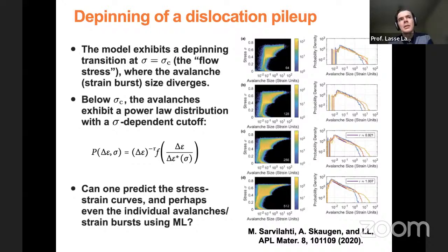And so now we would like to understand what we can say about this system. Of course, this system is a bit different from the previous one in the sense that now we have a well-defined depinning transition, or critical point, a critical stress value at which we get the depinning transition between pinned and moving states of this dislocation system. At this transition point, the avalanche or strain burst size diverges. If you look at the system below this critical stress or force, if you like, the avalanches exhibit a typical scaling form where you have a power law up to some cutoff that depends on the stress level.